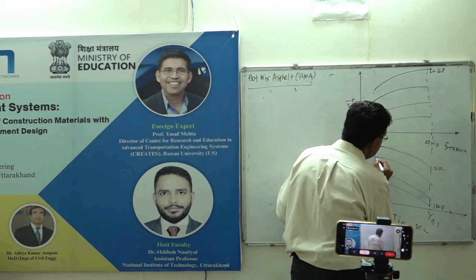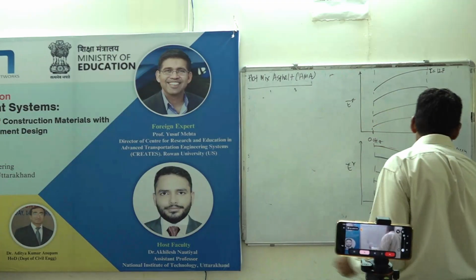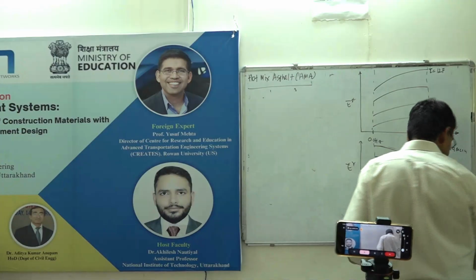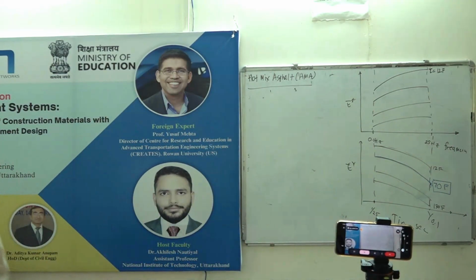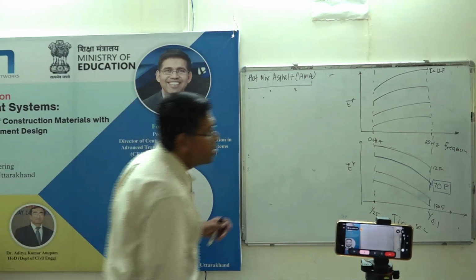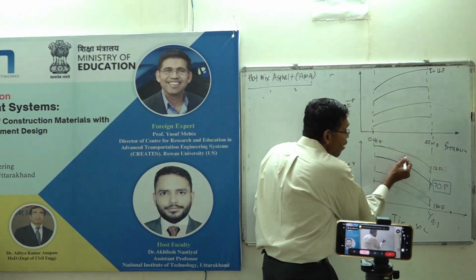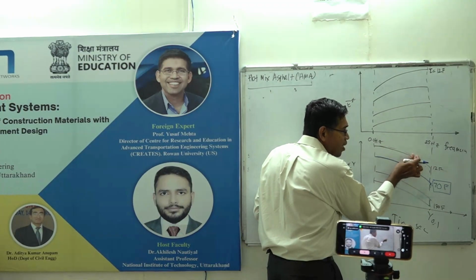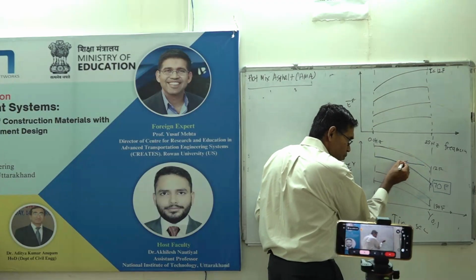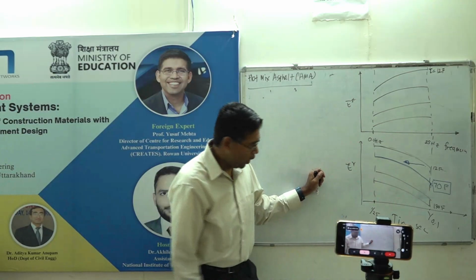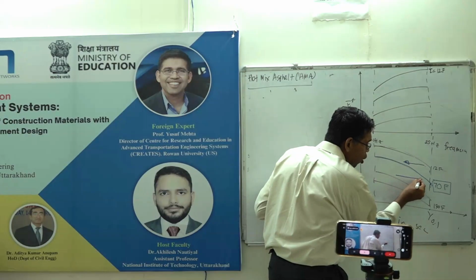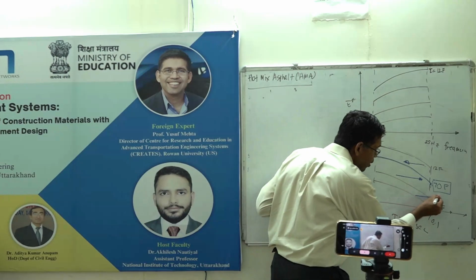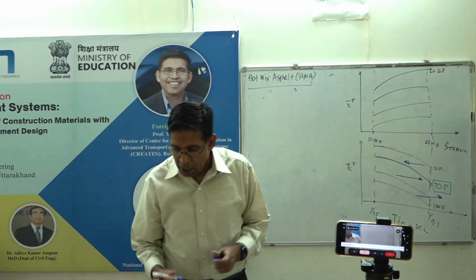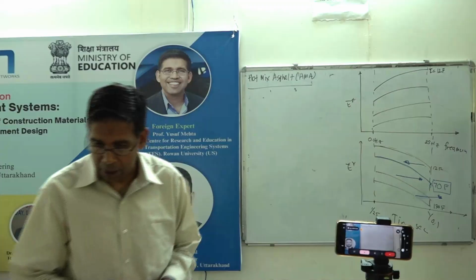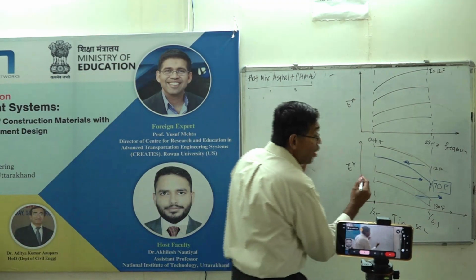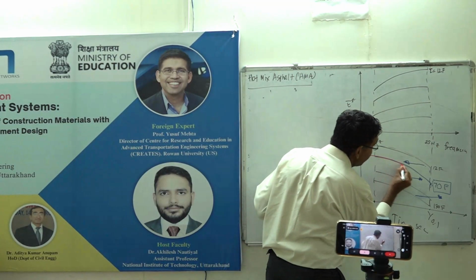Let's say that this is my, I'll pick this temperature, I like the 70 Fahrenheit, let's say. Okay. 70 Fahrenheit is my standard temperature, baseline, let's say, reference temperature. This is the beauty of asphalt concrete. If I just move this entire curve, I want everybody's attention, to the left, because it is colder than 70 Fahrenheit, right? And move this to the right, because it is hotter than 70 Fahrenheit. Correct? Does that make sense to you? Horizontal movement, no vertical movement, completely horizontal. What you will see is that it is true, all of them will directly follow a very smooth curve.